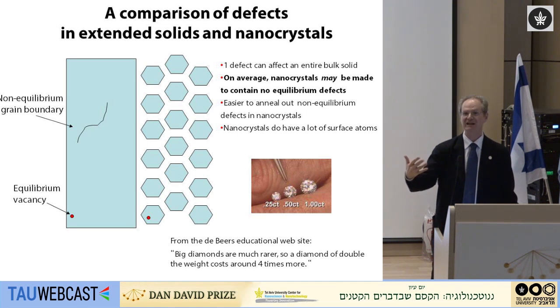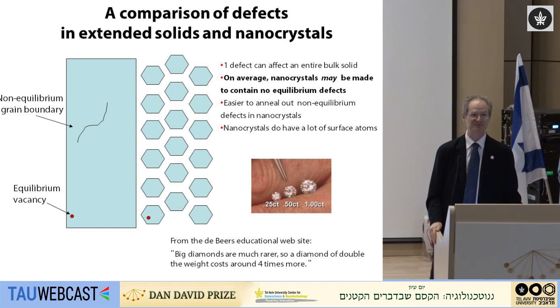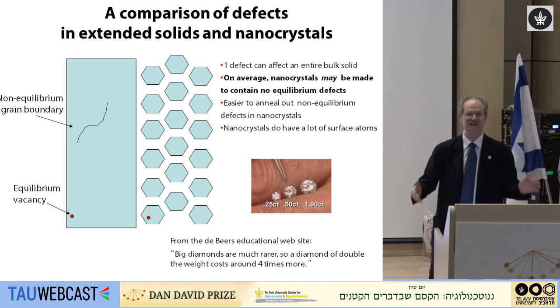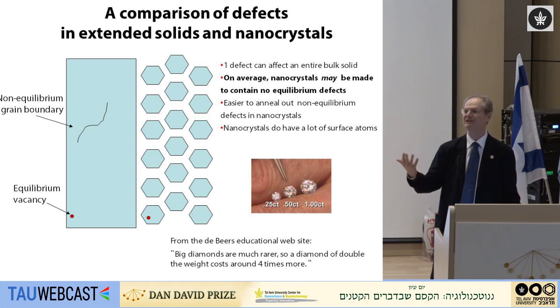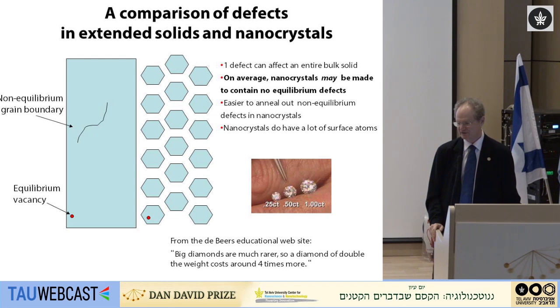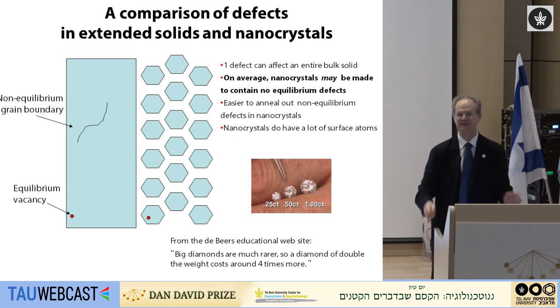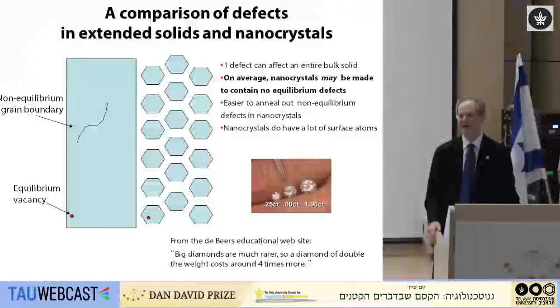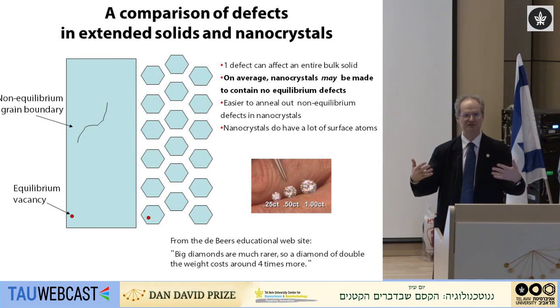Now, that is a kinetic defect, a defect that happened because of the growth rate. There are also equilibrium defects, which are ones that are present if just the number of atoms is very large. There will be a defect in there at equilibrium. But it turns out that for a typical inorganic crystal, a few electron volts, 4 or 5 electron volts per atom binding energy, the probability that there will be a defect in a crystal of 1,000 atoms is actually quite small for equilibrium. Okay. So if there's a defect present because the crystal was grown too quickly, then it will take a long time to anneal out if the crystal is very large.